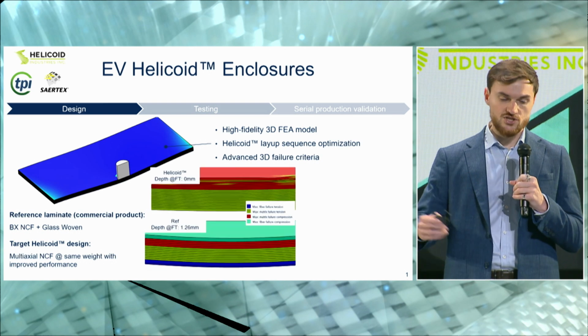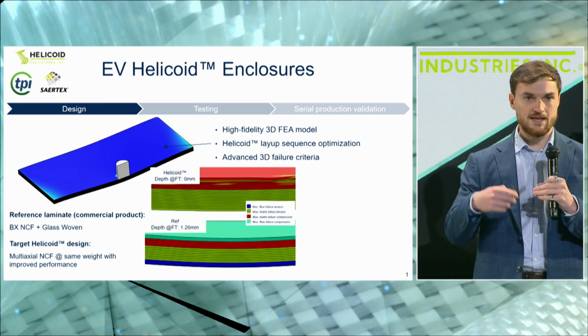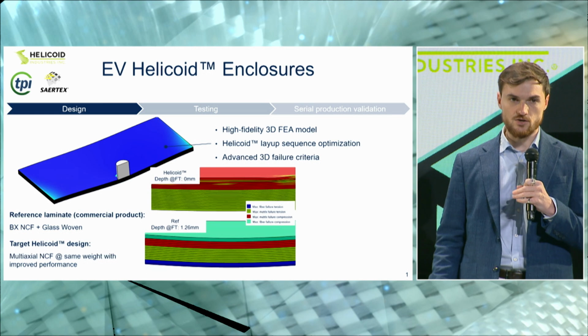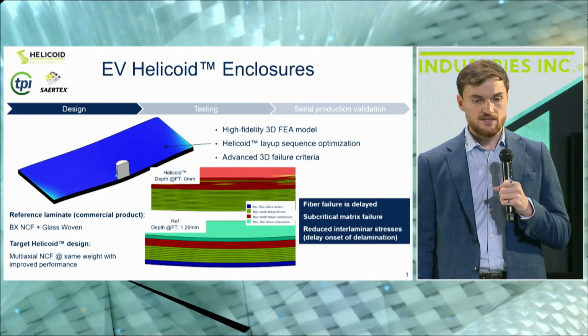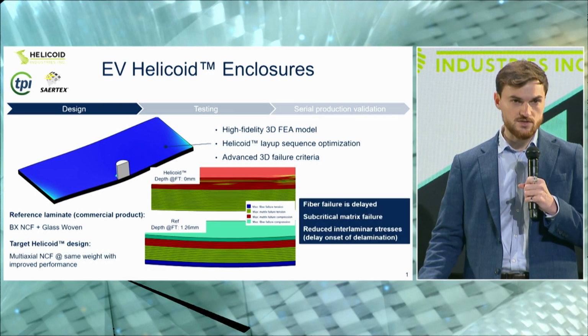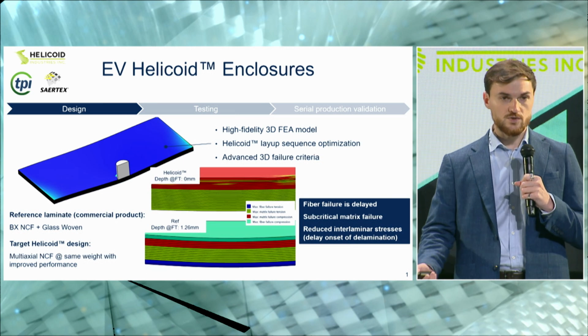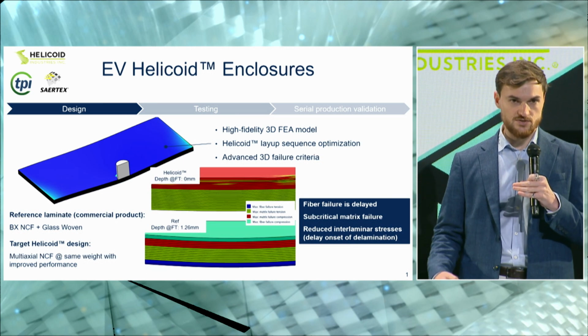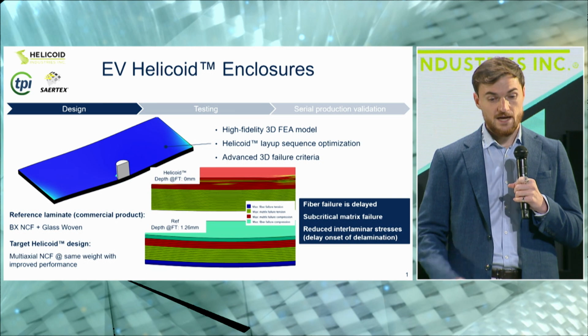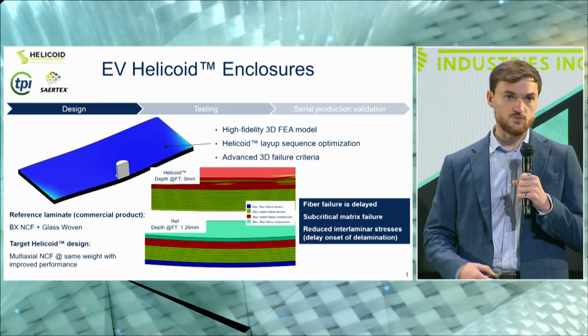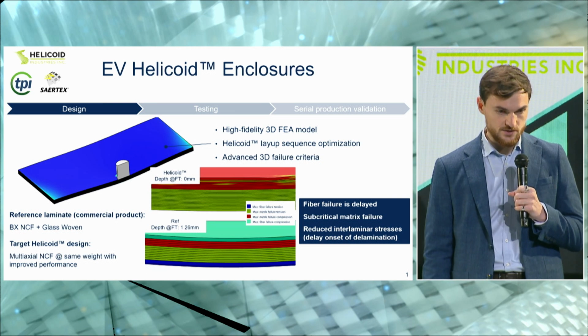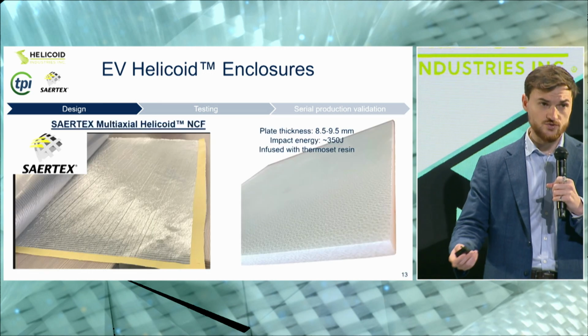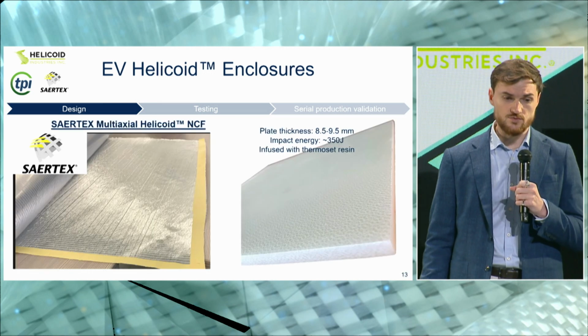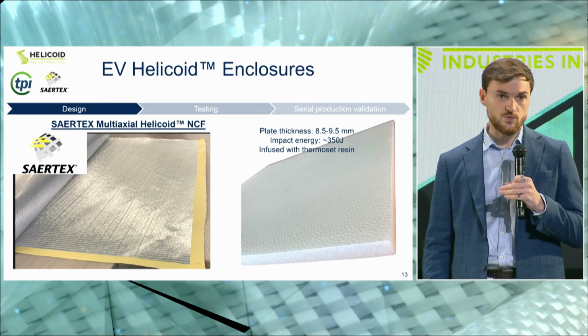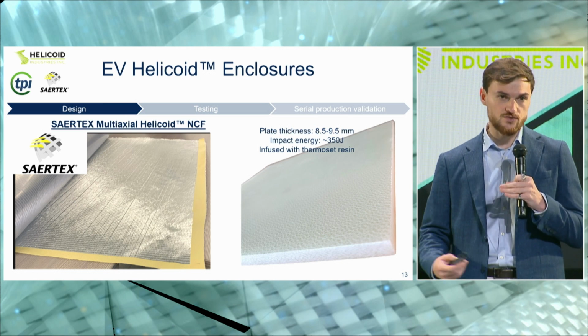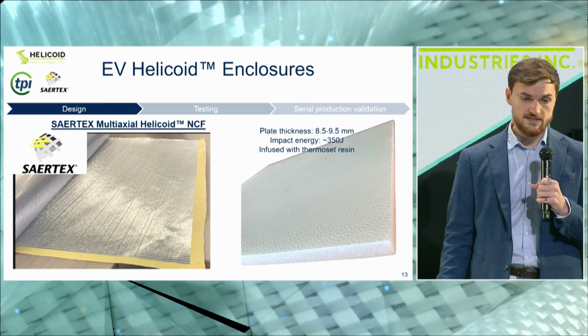Not going to spend too much time on the results, but the idea is that we can down select the optimal Helicoid layup sequence in such a way that we delay the occurrence of fiber failure. We promote the formation of this subcritical matrix damage that I showed you earlier, and we reduce interlaminar stresses so that we delay the onset of delamination damage. The next step was then to work together with Saertex to engineer the fabric and make sure that we can deploy the stacking sequence into a multi-axial NCF design.